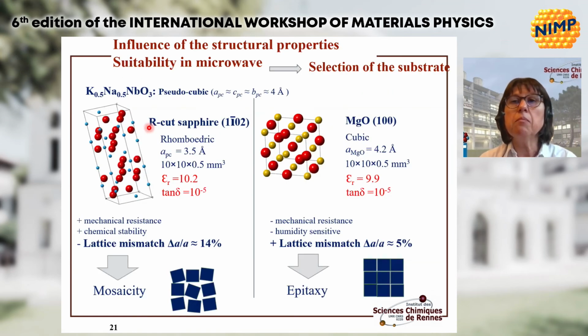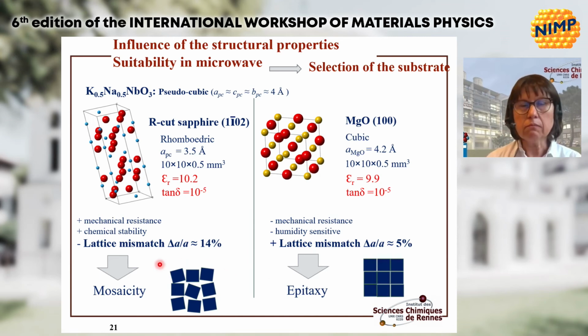Two types of substrate have been mainly chosen: R-cut sapphire and magnesium oxide. We have selected these two substrates because of their suitability for application at high frequency, essentially a very low tangent delta and quite moderate permittivity. Magnesium oxide presents a close lattice with KNN and a quite low mismatch of a few percent, which gives the possibility to expect an epitaxy. In contrast, with sapphire, a texture will generally be expected, with a quite higher mosaicity.